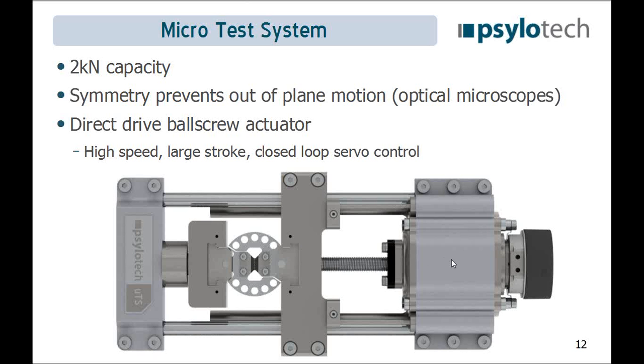The nice thing about the actuator, I mentioned it is direct drive, but it's very fast. The standard load frame is about as fast as a standard servo-hydraulic load frame. Not as fast as a servo-hydraulic that's been tweaked for high speed, but still much faster than a typical screw-driven load frame. And it's fast enough that you can do things like load control tests. It's also nice because it has a very large stroke in combination with the high resolution of the displacement that we have.